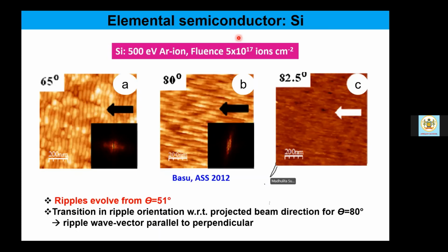So ripples evolve in silicon actually from an incident angle of 51 degree. And the transition in ripple orientation with respect to the projected beam direction takes place at an incident angle of 80 degree. So the ripple wave vector changes its direction from parallel to perpendicular. Very clear here, as we move from A to B.